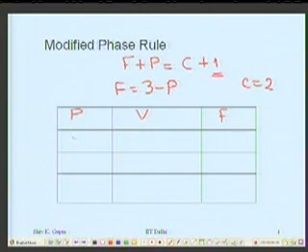If I have only one phase present in the system, how many variables shall I have? One. The variables in the system are pressure, temperature and composition variables. So if it is one phase, there will be one composition variable. And out of the pressure and temperature, I have already exercised pressure as 1 atmosphere, so I am left with 2 variables.